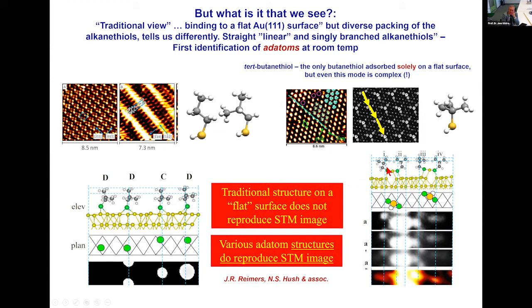We call it atomic scale gold mining. And then two alkane thiol molecules attack from the side. This costs energy, of course, to take out the gold atom, but the energy is recuperated by the double bonding of the gold sulfur. That is the common mechanism. And in fact, what we are seeing here is the first case of adatom formation at room temperature. If we compare with the more bulky tertiary butane thiol, there's no room that you can attack from the side. So this is the only alkane thiol that binds directly on a flat surface. So even though these molecules don't look all that smart, they are smarter than they look, because they can organize themselves in quite sophisticated ways.